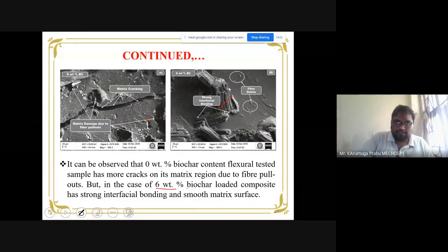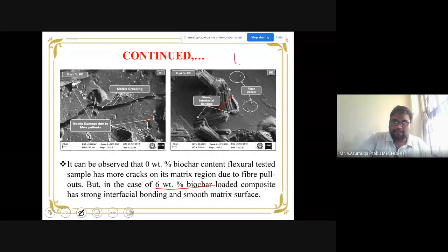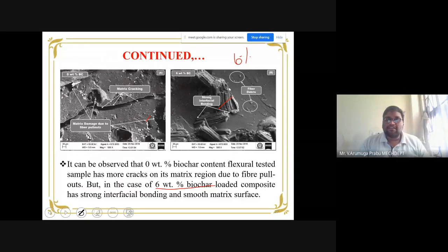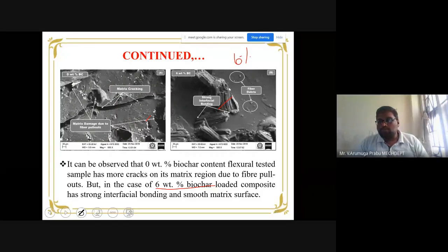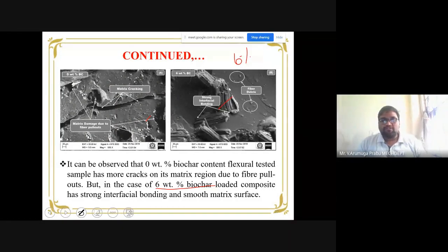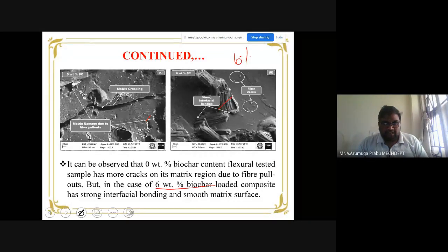Then followed by that, again a few SEM images, where here also the 6 weight percentage is shown. This is the 6 weight percentage addition of biochar. See, this SEM image I am going to take for the fractured specimen, and I am going to notice the fractured portion alone, how the fracture takes place. By doing some extensive microscopy studies at the fractured surface, I am able to notice whether my matrix gets debonded or fractured, whether my fiber gets fractured, whether my filler gets collapsed. Everything we are able to notice clearly with the help of scanning electron microscopic studies.